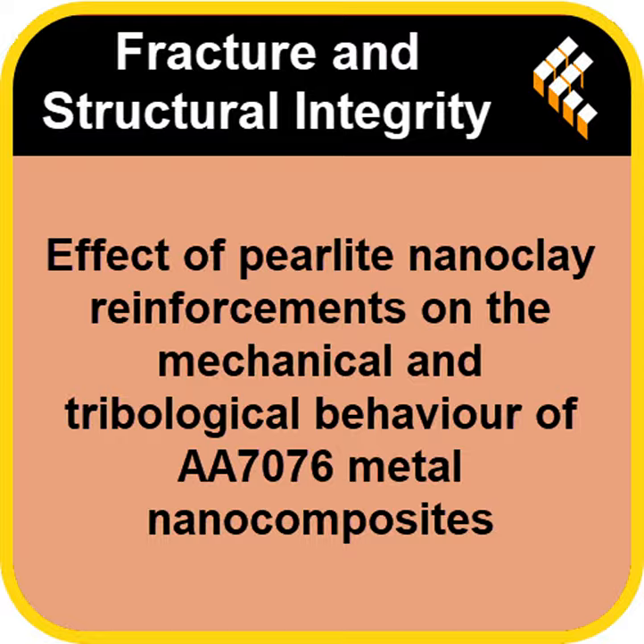And what's truly remarkable here, I think, is the reinforcing efficiency they got. This study didn't just nudge the performance up a bit. It achieved a shocking 38% improvement in tensile strength. And get this, using only 1.5 weight percent of this nanoclay. Only 1.5%. Yeah. I mean, when you compare that tiny amount to traditional reinforcements, you often need 5%, maybe 10% ceramic content for similar gains. So this looks like a massive leap forward for manufacturing costs and sustainability.